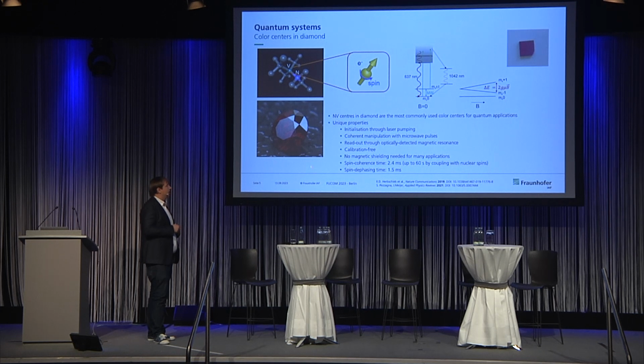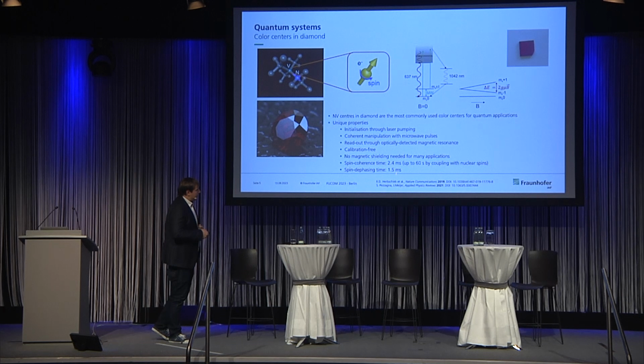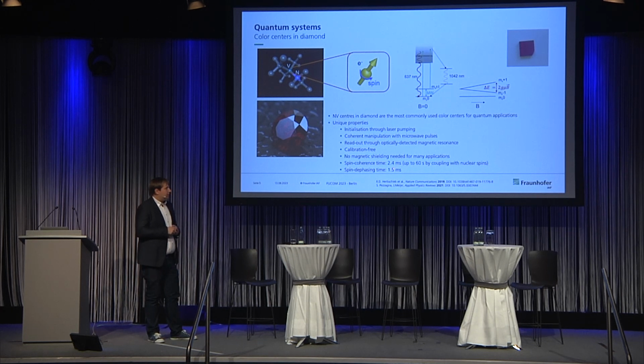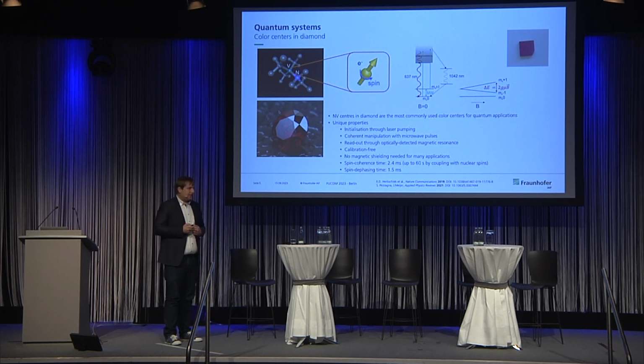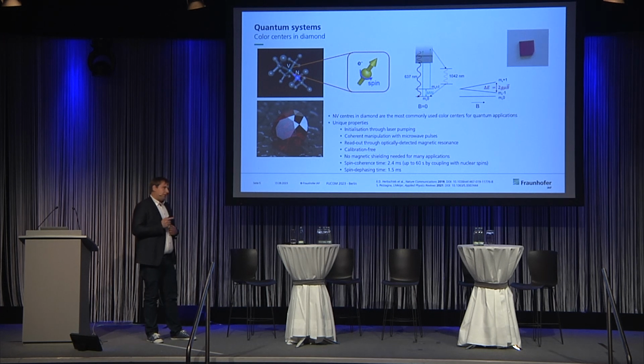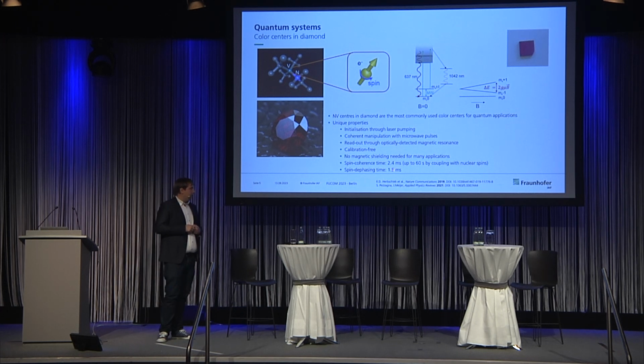We have some unique properties that are already talked about, but one is that the spin coherence time at room temperature can be in the range of milliseconds. If we couple with a nuclear spin nearby, we can reach seconds of coherence. That means we have a computational time of seconds. In comparison, superconducting qubits are typically in the 100 microseconds range, can also go up to milliseconds, but in this case at close to 0 Kelvin.